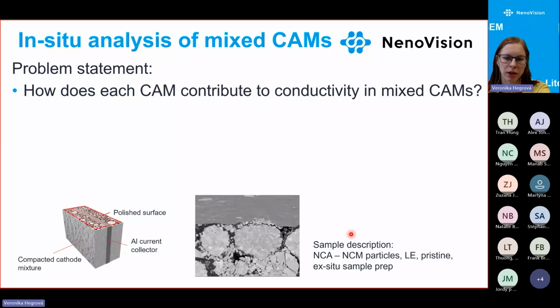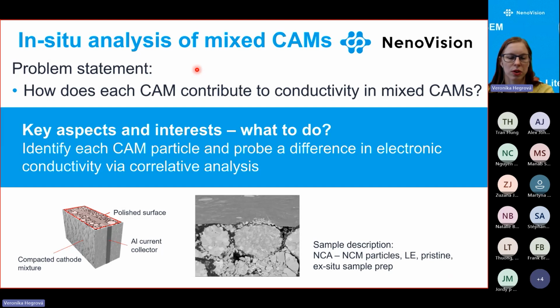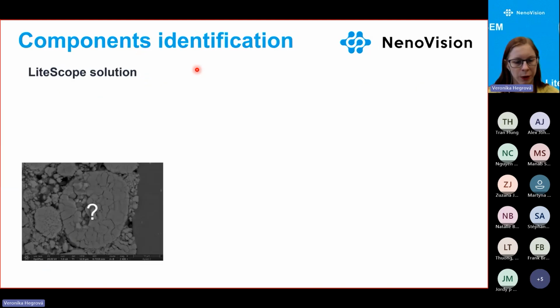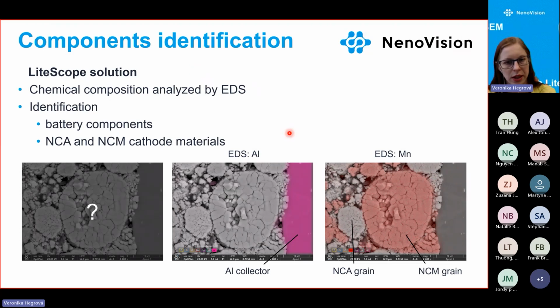If we have a look at another one, the sample for in situ analysis of mixed cathode active material: nickel, cobalt, aluminum and nickel, cobalt, manganese particles, liquid electrolyte, and this sample was pristine. So the question is, how does each of the different grains contribute to the conductivity in mixed cathode active materials? First of all, we need to identify each cathode active material, probe the difference in electronic conductivity, and correlate together and see what we have there. First of all, we use the EDS to analyze chemical composition. We see that we have the nickel, cobalt, manganese structures and NCA, the small secondary grain, and the aluminum collector.